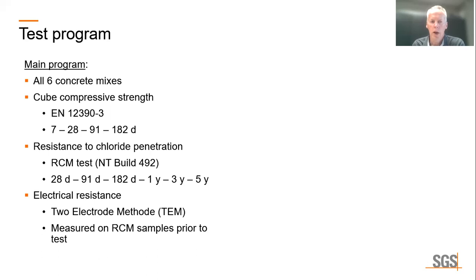This was done at 28 days up to 5 years. At the same time, we measured the electrical resistance by the 2 electrode method. This test has been performed on the RCM samples prior to testing RCM, so it was also performed between 28 days and 5 years.